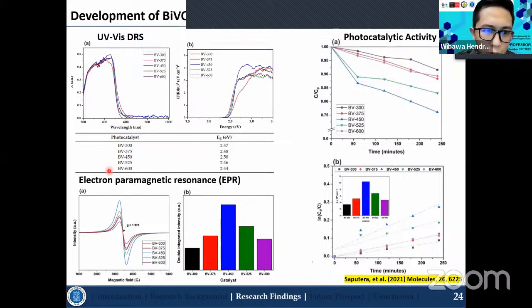And we also did electron paramagnetic resonance in order to find out whether there are defect structures in this system. And it proved that defects were generated as well, which is the vanadium 4+ associated with the oxygen vacancy. And we can see that there is a trend in here where the bismuth vanadate calcined at 450 degrees C generates the most defects compared with other calcination temperatures.